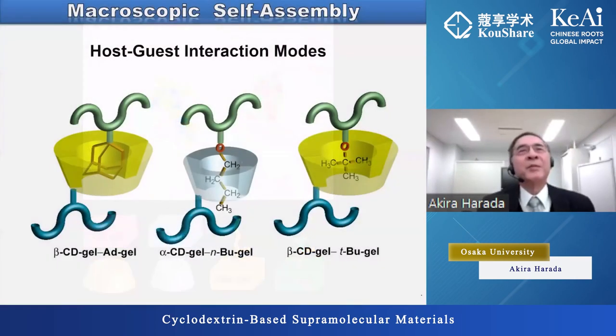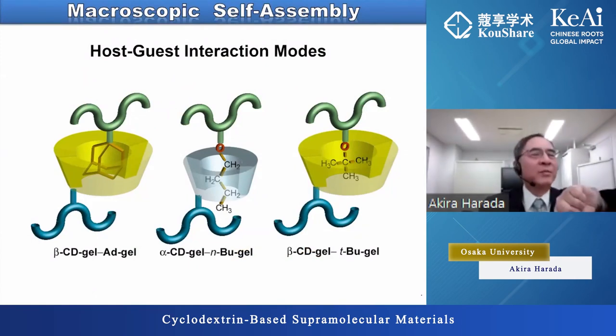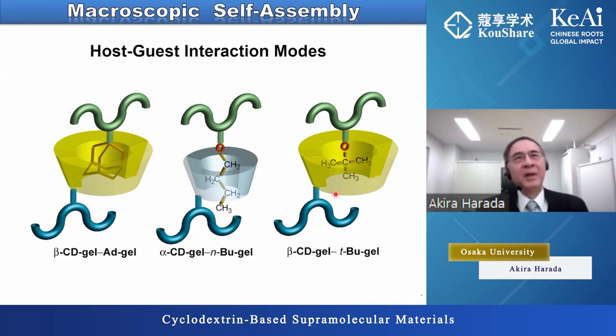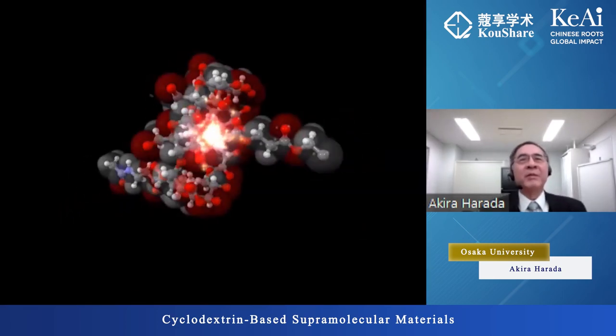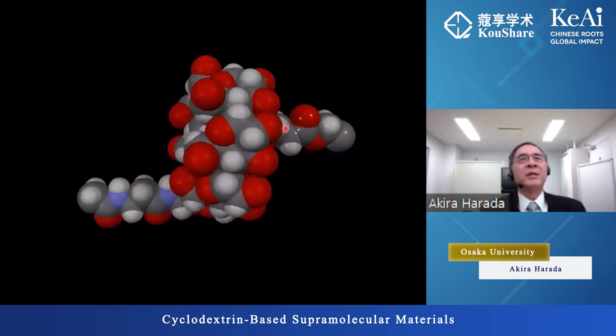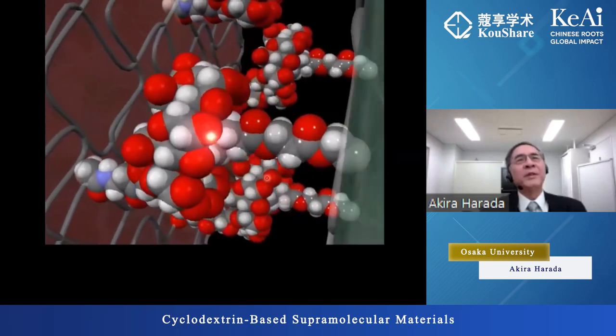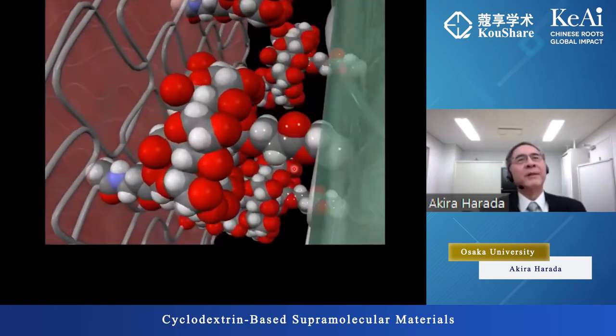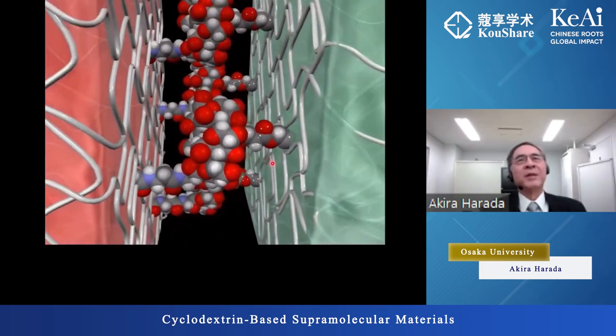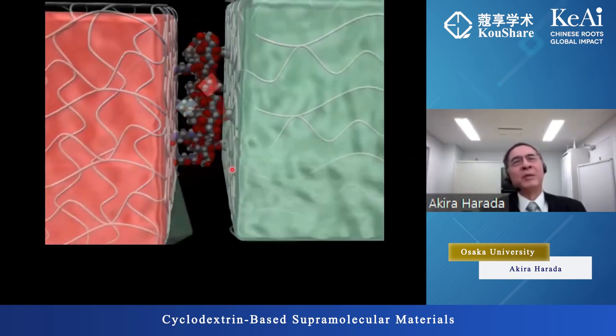Now, these are the host-guest interaction modes. The slim N-butyl group fits well in the small alpha cyclodextrin cavity, and the bulky adamantane group fits well in the larger beta cyclodextrin cavity. This system can be applied to differentiate macroscopic materials through molecular recognition of various guest parts. The beta cyclodextrin ring on the host gels selectively includes the adamantane group of the guest gel. The complex formation works cooperatively to give an assembly. The wider the contact surface, the more stable the binding is. So we are able to obtain